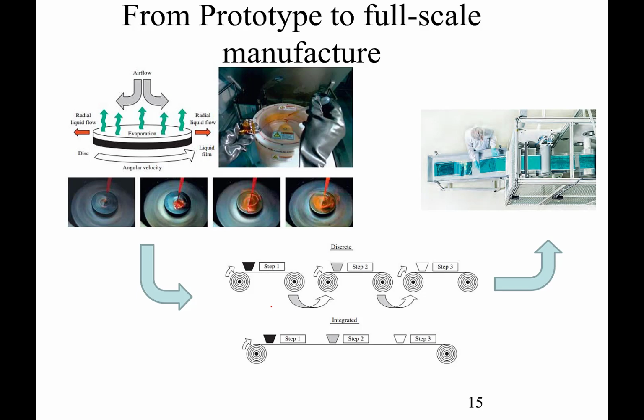Most of the time in my lab, for example, we work with something called spin coating. We drop some solution onto a spinning chuck where a glass substrate perhaps sits on top, and as the chuck is spinning, the liquid starts to get thrown off the side, the solvent evaporates, and we're left with a very uniform thin film. It's very useful for making one particular film, but it doesn't translate well into what we would call roll-to-roll printing, where we're trying to coat a whole large film that moves backwards and forwards across these rollers.